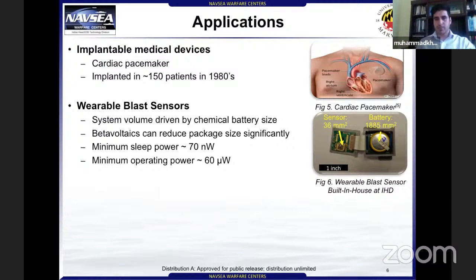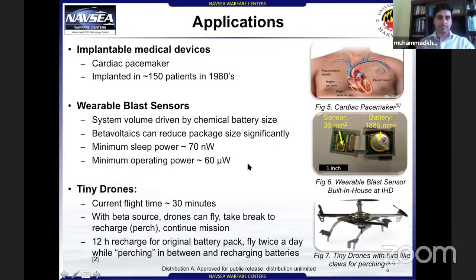As you can see here, our MEMS sensor itself is very small. It's only 36 millimeters square, but the battery size is much larger. Because of the battery size, we were not able to make this whole sensor package smaller. But if you use a betavoltaic power source, we can significantly reduce the package size. These are the power levels required for this sensor package, and we can easily achieve these power levels with a betavoltaic power source.